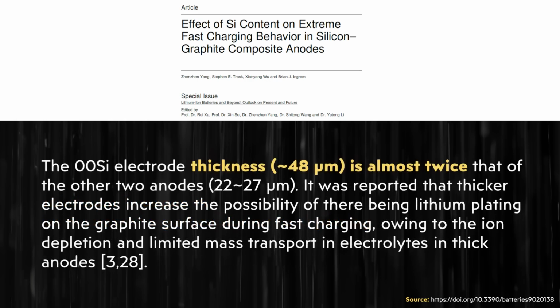Now, when it comes to the specific thicknesses of these anodes, it was mentioned here specifically that the anodes with 0% silicon had a thickness of around 48 microns, which was about twice that of the other two anodes, which had thicknesses of between 22 and 27 microns. And once again, that anode material thickness is a big factor when it comes to the lithium plating performance.